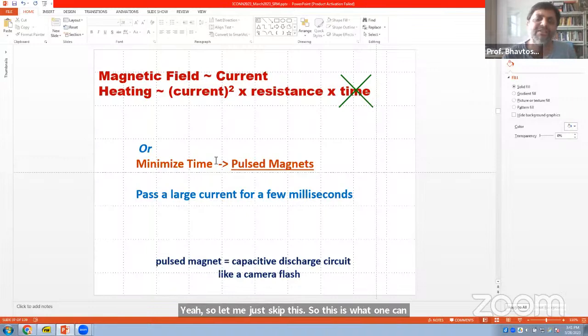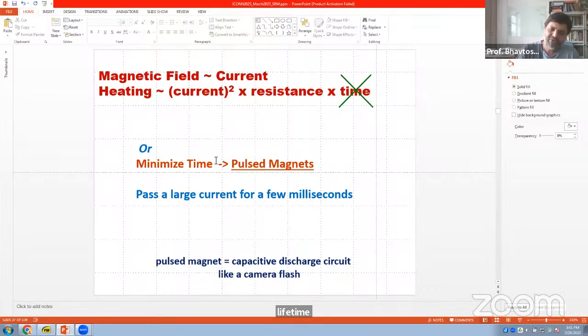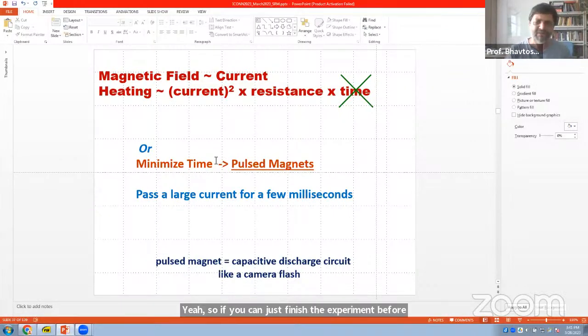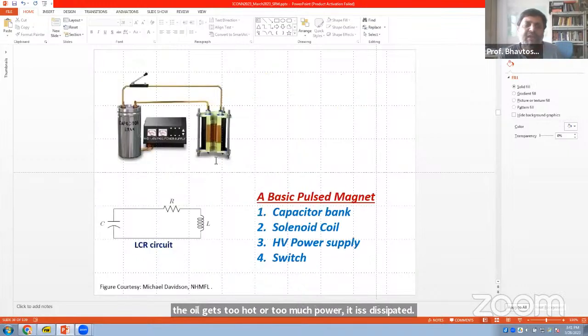But another nice idea, in my opinion, is to just minimize the time, because the field is proportional to the current, and heating is proportional to current squared times resistance times time. So if you can minimize the time and have the field on only as a transient, which lasts only a few milliseconds, and these milliseconds are, of course, a very long time, because radiative lifetimes are of the order of nanoseconds, so it's still a million times a typical radiative lifetime. If you can just finish the experiment before the coil gets too hot or too much power is dissipated, then you can make a small high field system, and that's the idea of a pulse magnet.